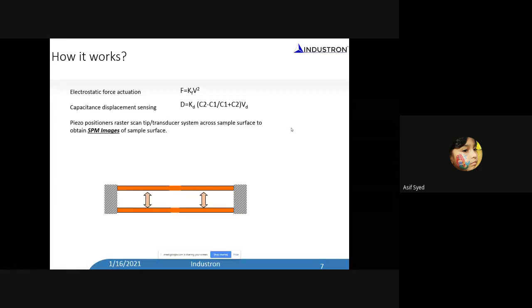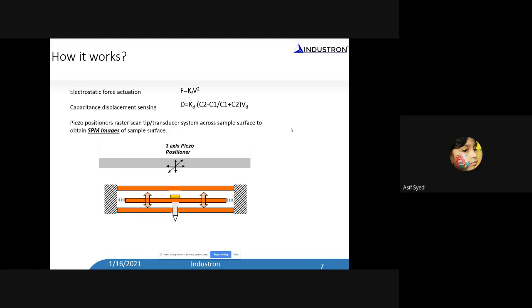Now, if you mount this transducer on a 3-axis piezo positioner, this is a piezo material, and materials science students know that if you apply a voltage to a piezo material, you can generate a mechanical action, a mechanical force. So we use that concept to move the piezo in the X and Y directions, as well as in the Z direction. So you can use it as a scanner, which is a technique used in the AFM, and we use a similar technique. It is a tube piezo scanner, and you can mount the transducer on it so that you can move this transducer in three-dimensional space. In this way, we can move tens of microns, about 50, 60 or 80 microns in X and Y, and about 10 microns in the Z axis. So now this transducer is mounted on this 3D piezo scanner, and we can scan this transducer.